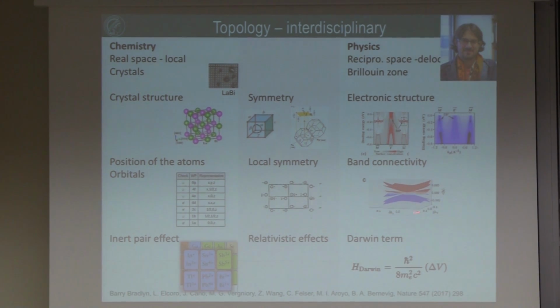Then if you want to have a certain band connectivity, you have to have the atom sitting on a special Wyckoff position. If you want to have an insulator, you have to have certain electron counting rules, and orbitals play a role. And if you want to have a relativistic effect, because this is really important in topological insulators, in physics you have the Darwin term, in chemistry we call it the inert pair effect, which means that if I have heavy atoms, the 6s electrons are contracted. We see this in chemistry very easily because bismuth is in group 5. You would expect normally bismuth 5+, but it's not. It's bismuth 3+ because the 6s electrons are contracted and they are not given away.